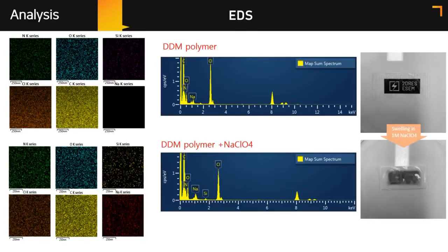This is EDS data for the hydrogel. The top is a DDM polymer washed in DI water, and the bottom is the DDM ClO4 polymer washed in DI water. Sodium atoms were evenly distributed in the polymer washed with NaClO4 solution. Look at the picture of the polymer before and after swelling. The polymer color is changed after washing, and the reason is that the NaClO4 is trapped in the hydrogel.